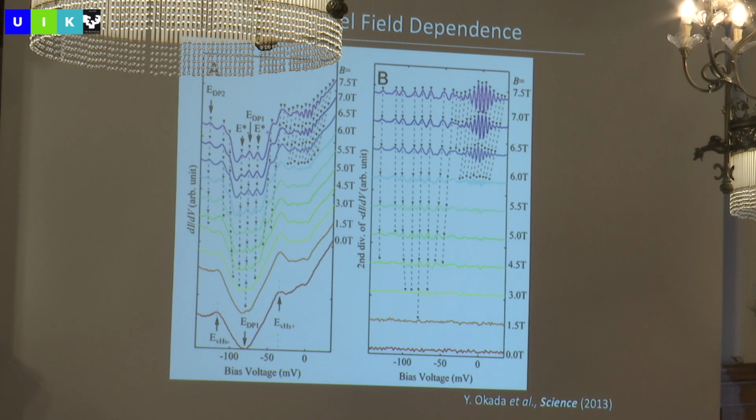So there is that. And the second is to actually look at that carefully. We did notice that, look, these things are riding on top of some background. And you have to think about that background as well. Each Landau level is closely spaced, so they actually overlap each other. When they overlap, what you're seeing with your eye is not the full Landau level peak. You're seeing a bunch of overlapping peaks, really. So that's what gives you the background also.